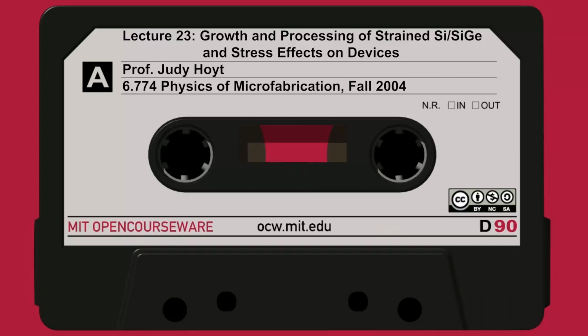And in fact, here on slide 14, I'll just walk through some of the older data. This was from 1992 by Welser. These were the first strained MOSFETs that were fabricated, where he made a thin layer of strained silicon on relaxed silicon germanium and then just implanted it and made a silicon MOSFET with a source and drain. It was an N MOSFET.